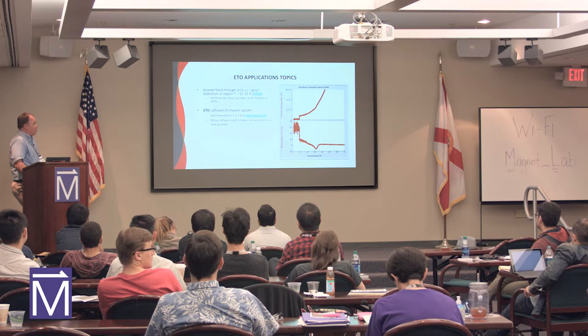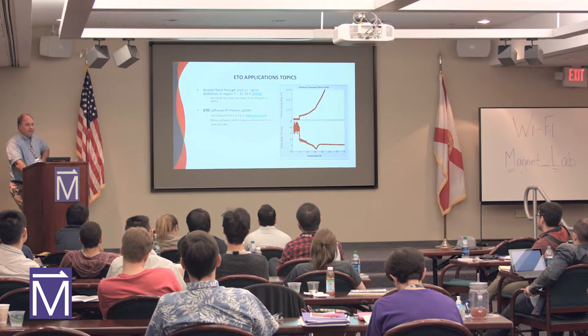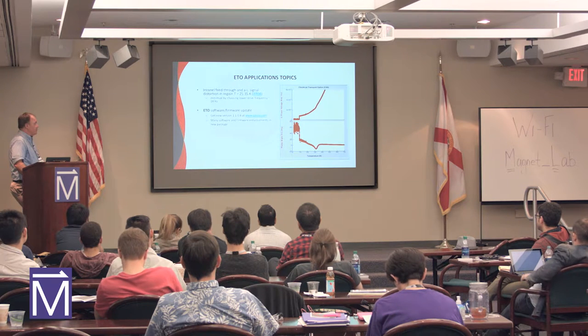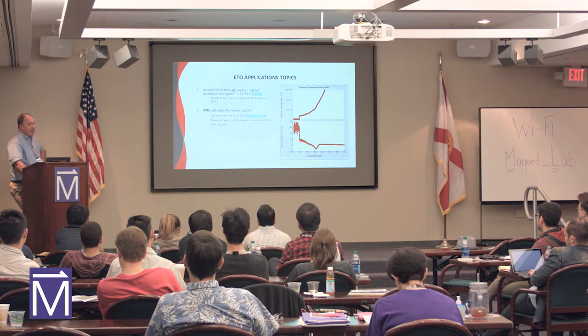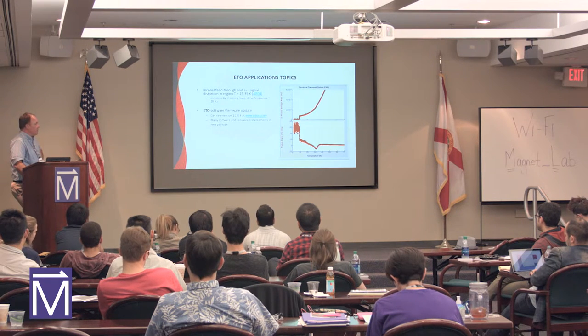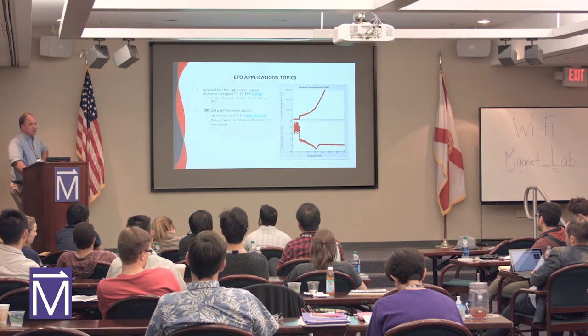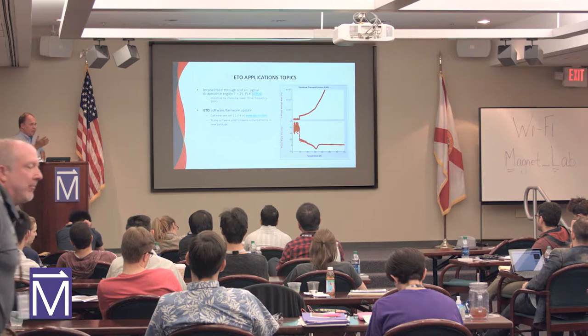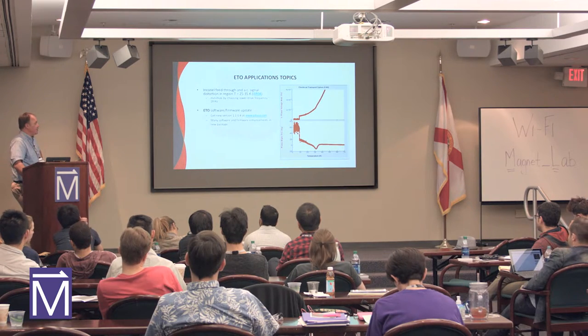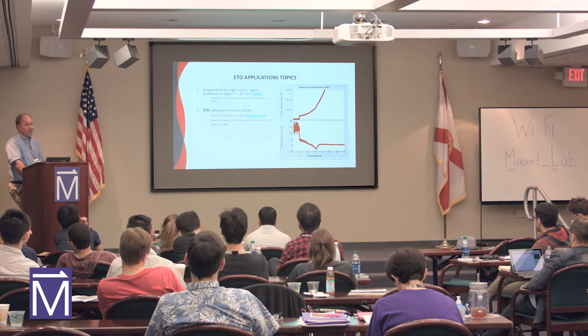We wrote an app note about the feed-throughs. The vacuum feed-throughs have Inconel in them, and they have a frequency response, where the resistance change is a function of frequency. So there's an AC response to the resistance of the Inconel feed-throughs as a function of the system. So you can see this effect.